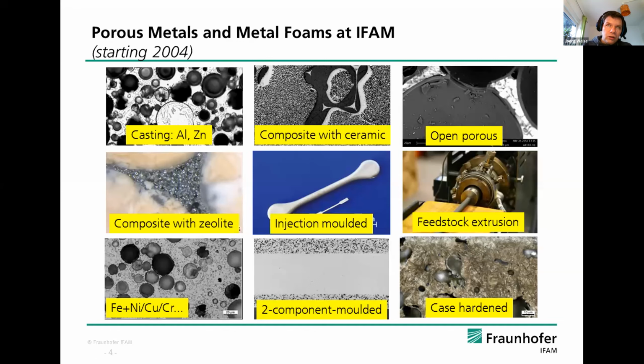Syntactic foams are mostly known to be closed porous, but with some special treatments, you can open the structure. You can see on the right side on top two sintered spheres, or the sintering neck of two hollow spheres. The hollow sphere structure was later infiltrated with metal, and the sintering neck was then opened using a high pressure treatment with water. We combined such open porous structures also with active materials, like for instance zeolites.